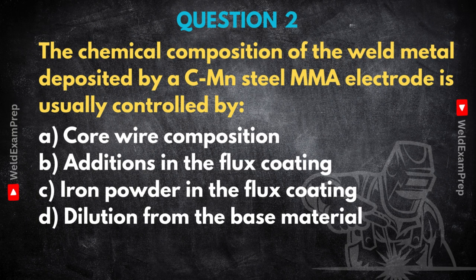It does seem that way at first glance, but the answer is definitely B, additions in the flux coating. Here's the thing. While the core wire provides the, let's say, base iron and some carbon manganese, it's that flux coating that's packed with all sorts of clever stuff. Alloying elements, maybe extra manganese, silicon, perhaps even nickel or chromium, depending on the electrode type, plus deoxidizers to clean the weld pool, slag formers to protect it, sometimes even materials that generate shielding gas. Wow, okay. And these additions are specifically designed to transfer across the arc into the molten weld pool as the flux consumes itself. So they massively influence the final chemistry. That's how manufacturers create electrodes for specific strengths, toughness, corrosion resistance, far beyond what the simple core wire could do alone.